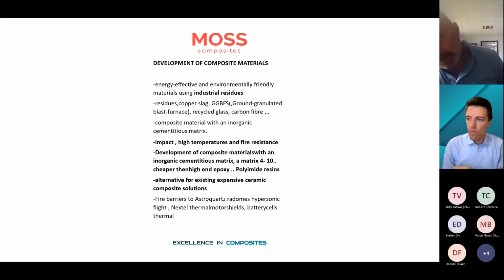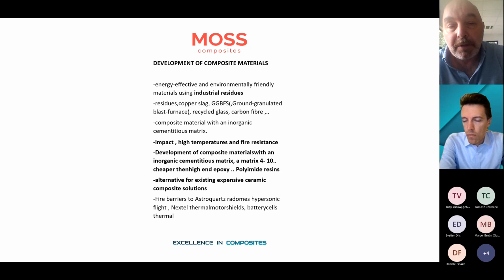The reason for this inorganic cementitious matrix is that, first of all, they have the capacity for very high temperature, which is a problem for organic resins. I think polyimide only goes to 300 or 350 degrees, and it's also very expensive. So the resins we are working with go much higher in temperature. They give the fibers the possibility to go to their limit temperature use. For example, carbon fiber starts oxidizing at 700 degrees. The polyimide will be gone before the carbon fiber starts oxidizing, but with our inorganic matrix, it's the other way around. It depends on what kind of formulation we use, but we could go up to 1300 degrees.